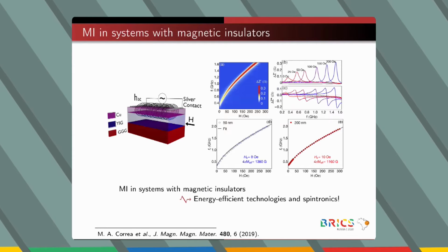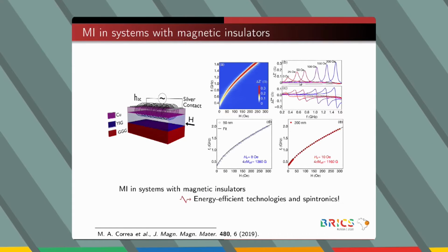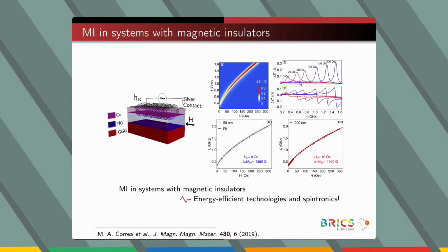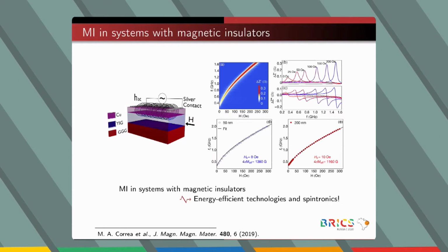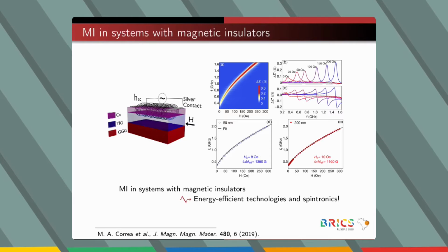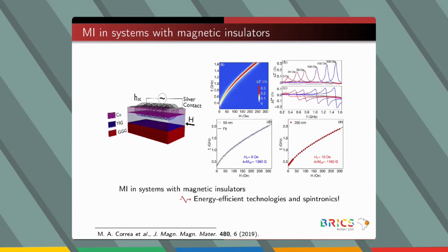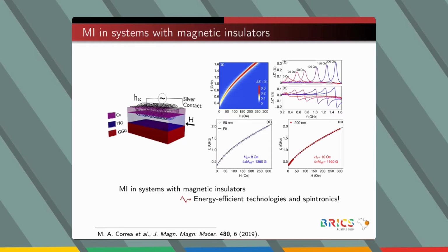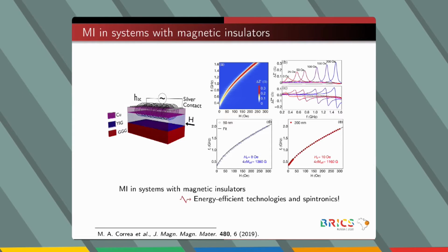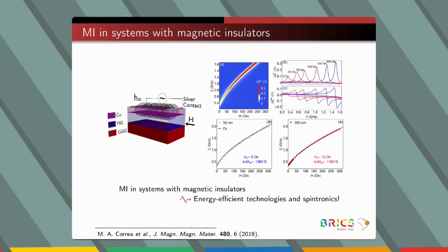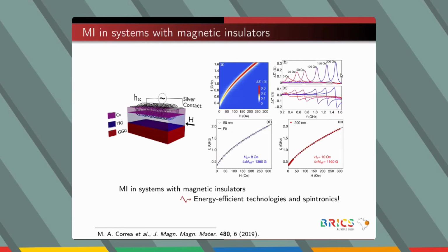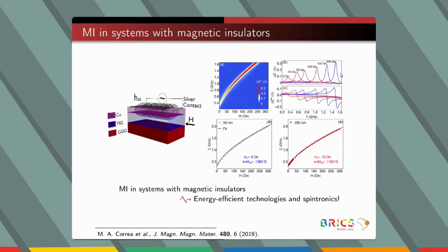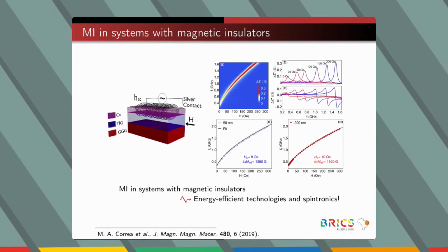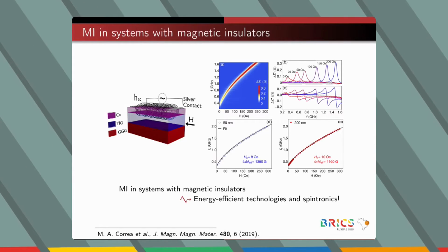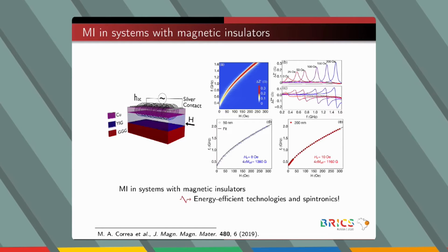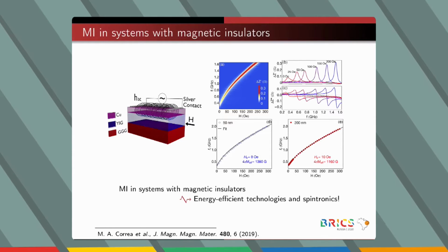Finally, more recently, we investigated the magnetoimpedance in systems with magnetic insulators. We produced a system that consists of an yttrium iron garnet covered by a copper layer, and found that despite the different electrical features, the response is very similar to that obtained for magnetic conductors. These results are very important because yttrium iron garnet is a material with great appeal in the context of spintronics and to the development of devices with optimized energy efficiency.